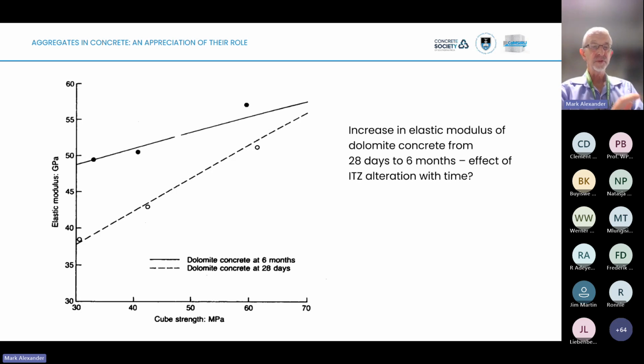be understood. This effect that we see on this diagram is really largely an effect of the interfacial transition zone. It represents a densification of that zone with time due to ongoing deposition and hydration within that zone. We can actually take that effect out. We can sort of engineer this zone by using very, very fine fillers, SCMs like silica fume.